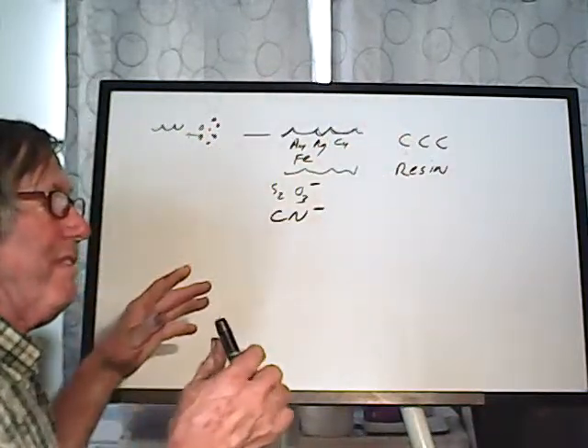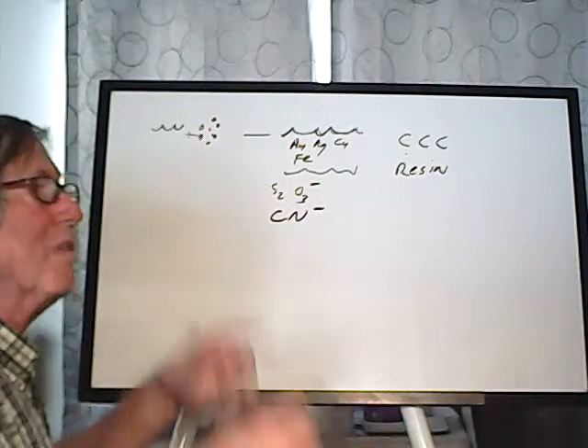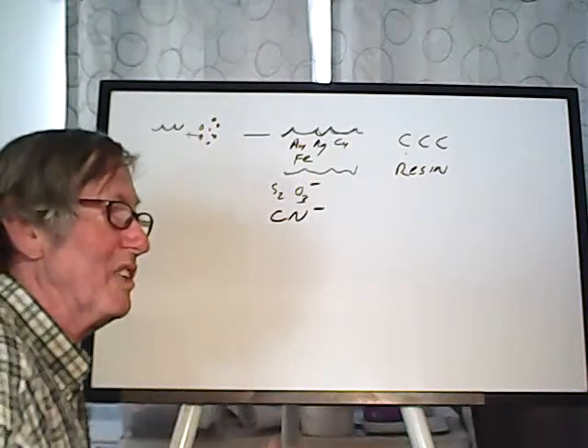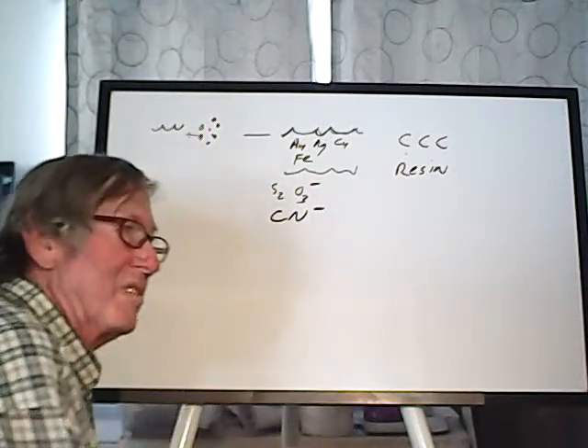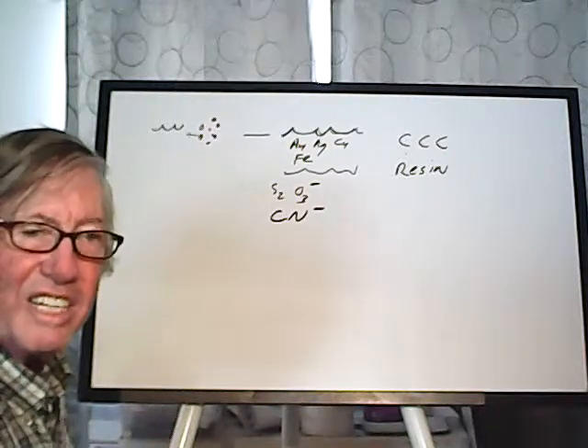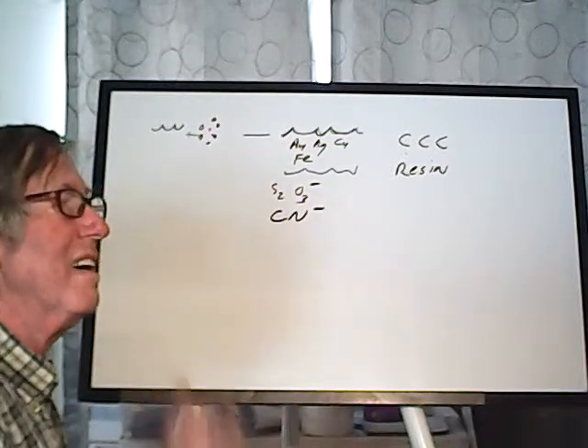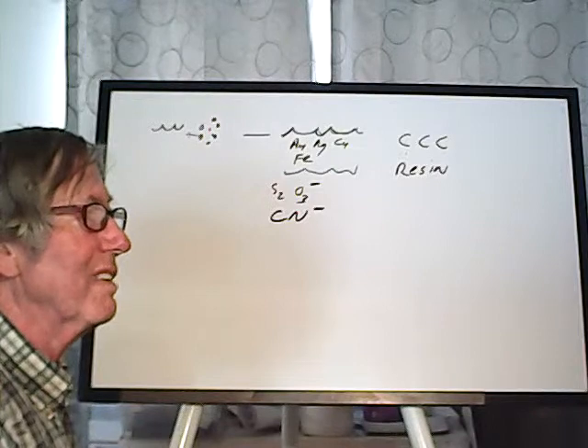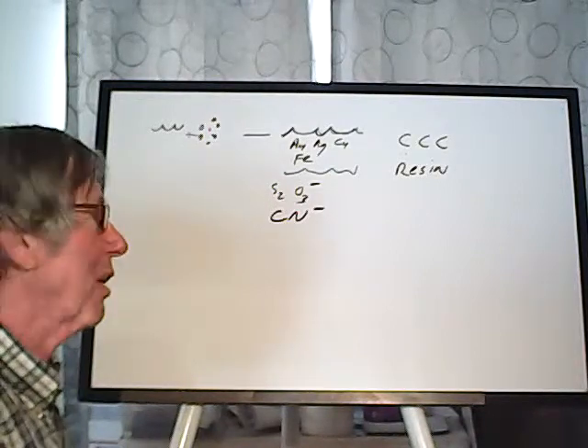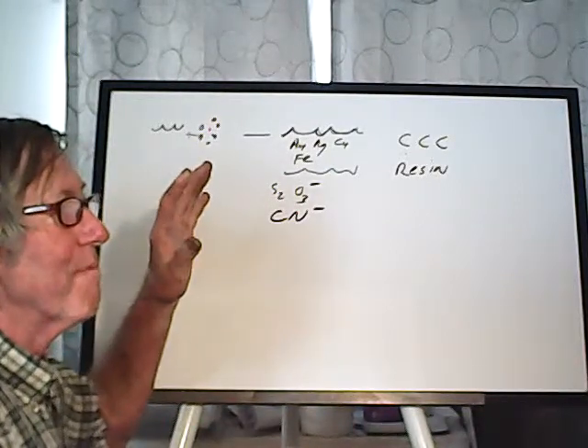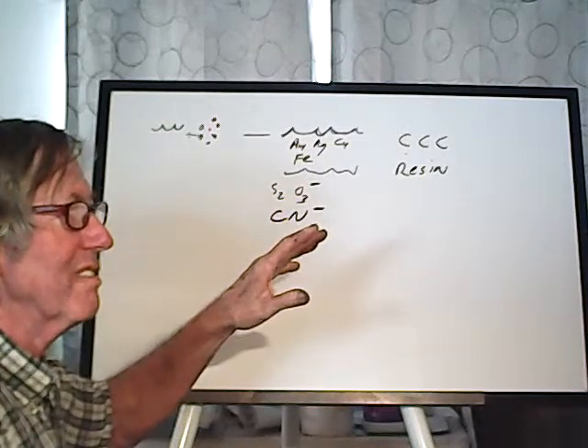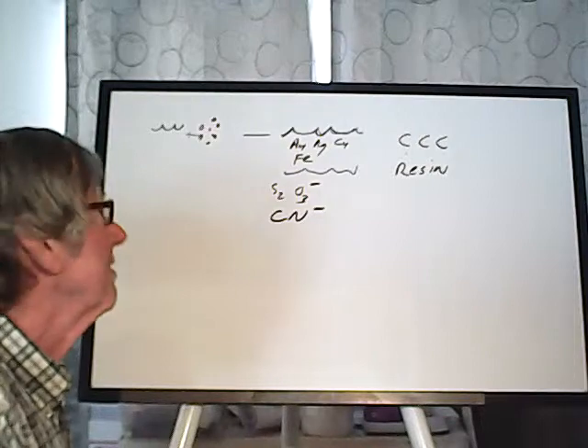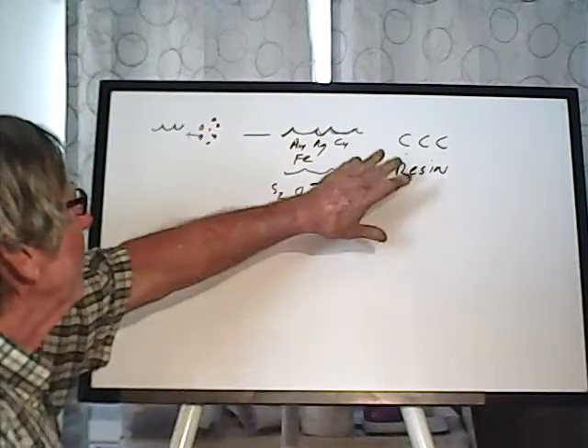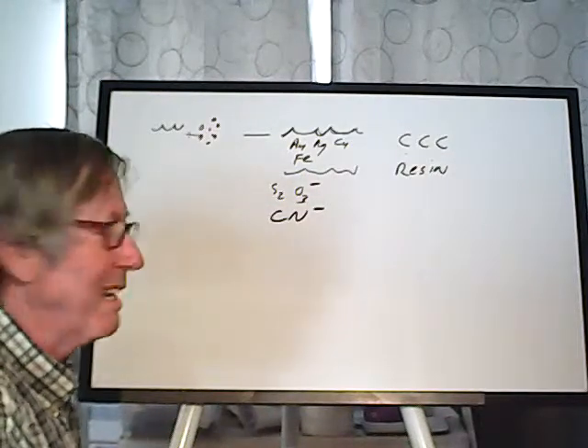Carbon is overall less expensive and more efficient and works at lower concentrations. You can efficiently adsorb the gold onto the carbon, adsorb, A-D-S-O-R-B, at very low concentrations. It's not nearly as good trying to precipitate it with zinc at real low concentrations. Okay? Resin does basically the same thing.